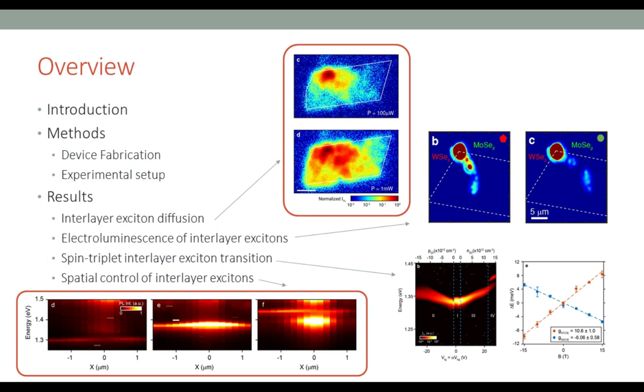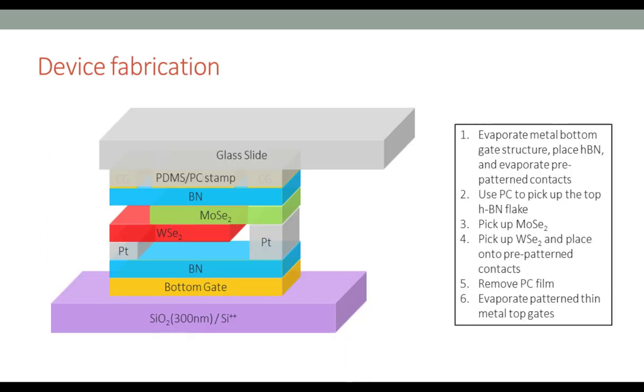So we'll start with the device fab. We use a very standard 2D material stacking technique. This involves a glass slide with PDMS and PC. PC is our sticking layer. What we do is we prepare a substrate with silicon oxide. We put our gates and then a BN and contact platinum.